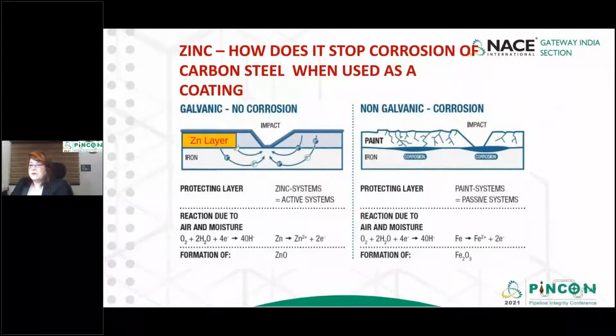When an organic coating is provided, it gives barrier protection for above-ground structures, and if the coating is damaged, steel corrodes freely and forms ferric oxide. These are normal paints. These are ferric oxides. With the formation of ferric oxide, you can see the corrosion has started.